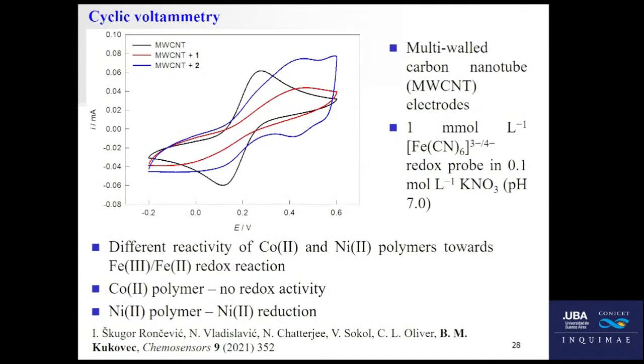So as I said, we have cobalt and nickel in the same synthetic conditions. Crystallography revealed they are isostructural, so we wanted to check if there is any difference in the end for these two types of compounds. So we did a cyclic voltammetry study on these two, but not the regular one. We used multi-walled carbon nanotube electrodes. The compound, either nickel or cobalt, was dispersed in these nanotubes, and that served as the electrode. And we used the cyano-coordinated hexacyanoferrate, iron 2 and 3, their mixture, as the electrode probe.